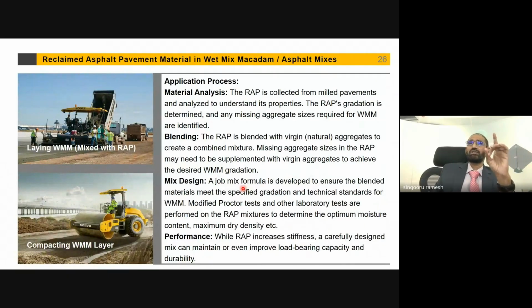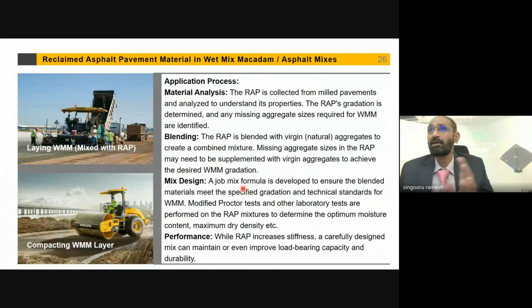Again, see, whenever we are using this RAP, we have to do the mix design. Mix design should be conducted and the test results have to be examined. And if they are within the range of acceptable norms, then only that mix has to be used. So why is mix design required? Because the percentage of the ingredients will be decided. Sometimes RAP may be decreased, sometimes RAP may be increased, or bitumen percentage may be decreased, bitumen may increase, or filler may be increased or decreased, binder may be increased. All these combinations will be worked out. See, the performance while RAP increases stiffness, a carefully designed mix can maintain or even improve load-bearing capacity and durability.